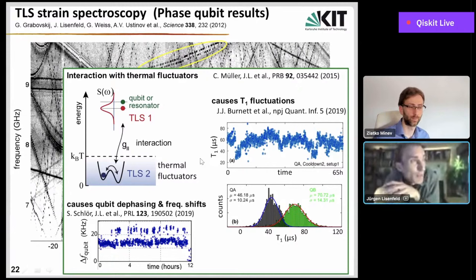And apart from quasi-particles, there's of course also surface spins, which are known to generate flux noise in, for example, DC SQUIDs. However, also for surface spins, there's no really good argument why they should have such slow dynamics here. But everything is very well explained by these defects.